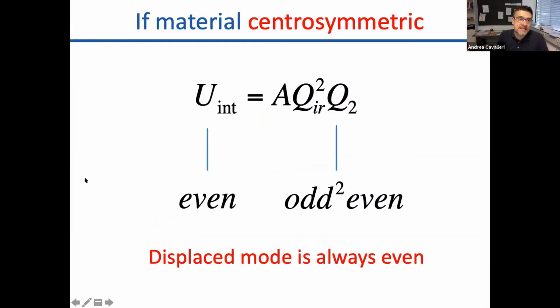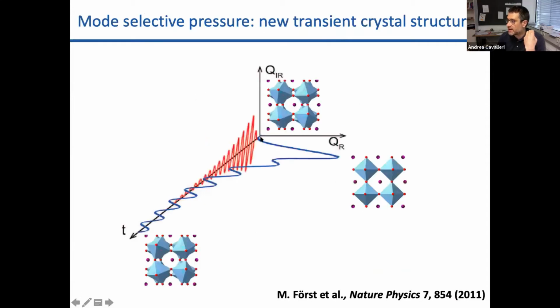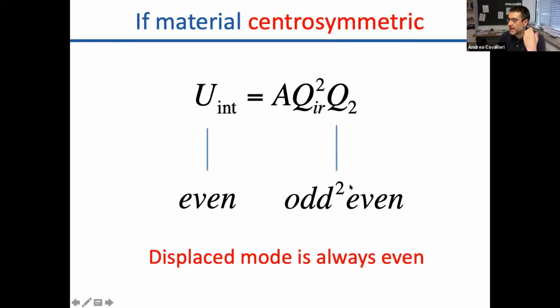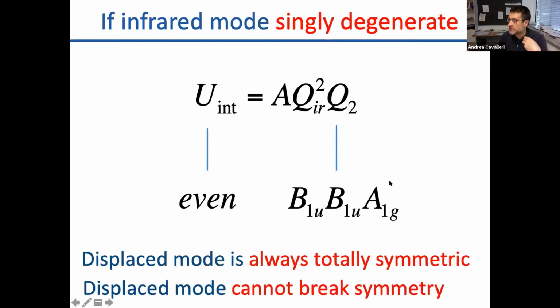So for various reasons, those of you that don't want to get into this should just take my word for it. If the material is centrosymmetric, if the driven mode is odd, the displaced mode, so this guy here, will be even against inversion. And furthermore, in most cases, it will also be a totally symmetric mode. So the mode that is being displaced in this way will tend to retain the crystal structure and the symmetry that the material had before being excited.